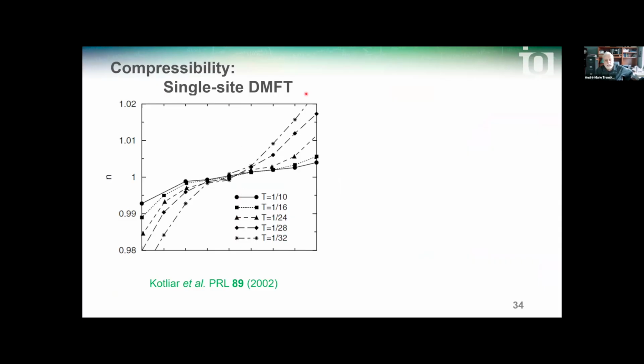Let's start with single-site dynamical mean field theory. On the left is the filling as a function of chemical potential for various temperatures. As you can see, the slope becomes sharper and sharper as temperature decreases. Correspondingly, it's not clear here, but it appears in another plot of that paper, corresponding eventually to a divergence of the compressibility approaching n equals 1.